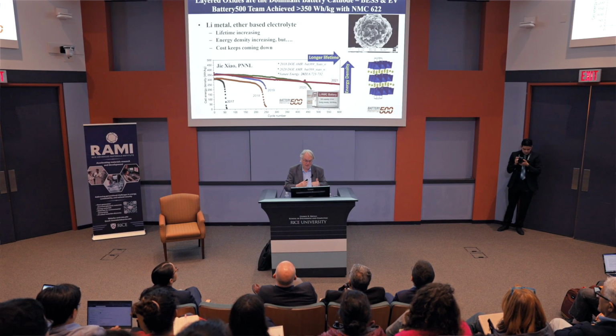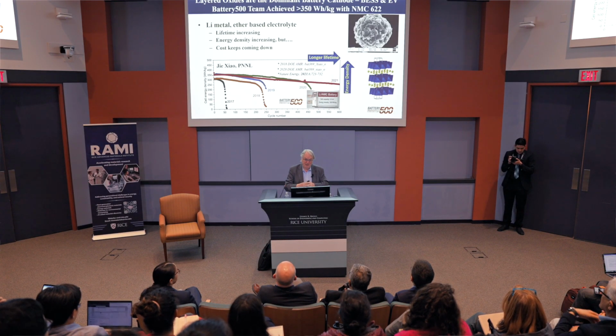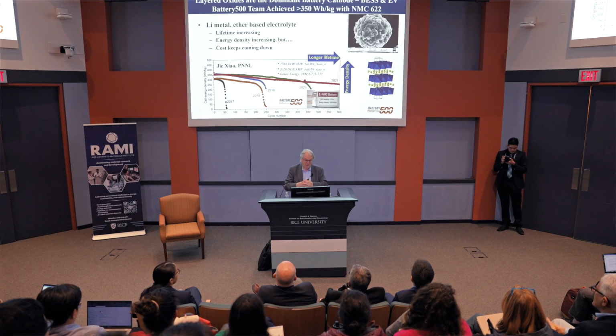So we use lithium metal here. We use a new electrolyte, an ether-based electrolyte, same as what Exxon used 50 years ago. So ether-based electrolytes plate out lithium much better. And I expect in materials science, you don't talk much about electrodeposition and metallurgy anymore. But the issue with lithium is the same as with zinc. These materials like to form dendrites rather than a nice smooth surface. So we're looking at that. We're increasing the energy density a lot, but I'll show you some issues there, and the costs keep coming down.